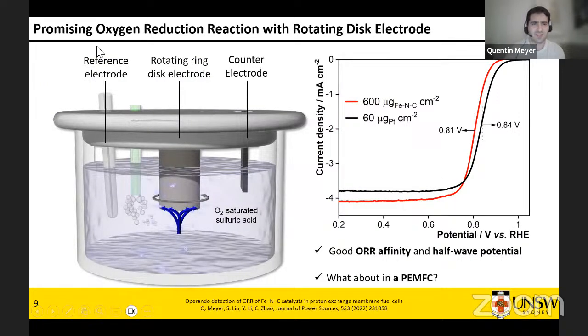So this is how you would start a study of a fuel cell catalyst. First, you deposit your catalyst into a liquid cell. You bubble it to saturate with oxygen, and you get these kind of curves. The half-wave potential is a metric we look at to find out how good the catalysts are. You get 0.81 for your iron-nitrogen-carbon catalyst, which is the material I'm looking at, which is without platinum, and you get 0.84 for platinum. So quite a good start.